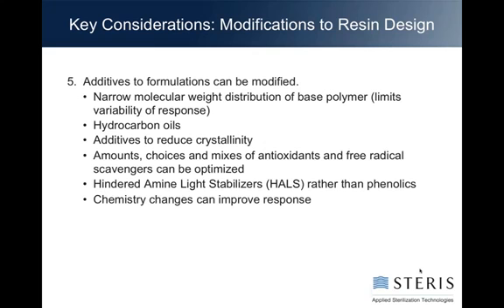Think about the molecular weight of a long chain polymer. How long that chain is impacts the molecular weight. You could have in a bottle of resin a wide variety of molecular weights of chains. The more narrow that distribution is, you'll limit the variability of your response. So when you get to a resin that's really, really good, those properties, the effects will be very pure and very discrete. If there's variability, you may have more effect on the ones that are shorter versus the ones that are longer, so you can get some very different things going on all at the same time.